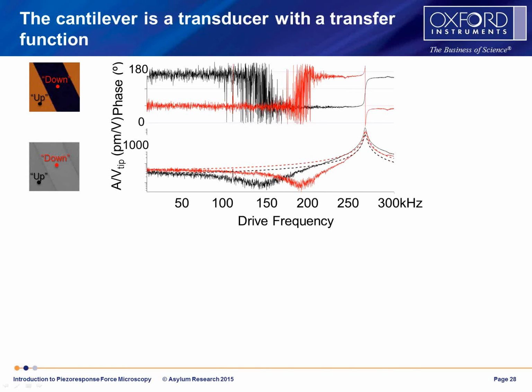This frequency dependence, in retrospect, isn't very surprising. The cantilever is a mechanical object. It has a transfer function. By transfer function, I mean that the output, its vibrations, depends on the input frequency and amplitude. So you can think of it as a sort of tune. These graphs show the phase and the amplitude over the domains in the data from the previous slide. I called the red one the down domain and the black one the up domain. The phase is positive here, and then up at about 150 it flips. There's a kind of complex structure in that, this transition here. And then here is the contact resonance where the phase flips and the amplitude peaks.